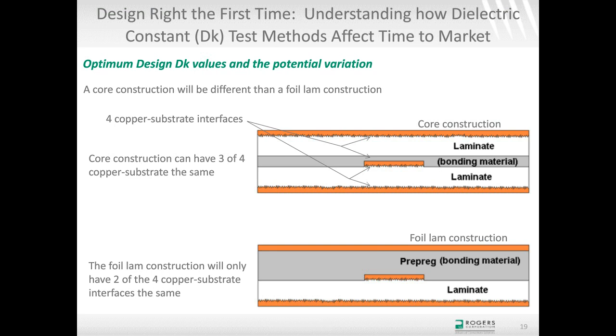In that case, we understand and we would know the copper surface roughness of three of the four copper substrate interfaces. We would not know the fourth one, which would be the smooth side of the bottom laminate. And the reason we say that is because we know what that smooth copper is. We know what that surface roughness is when it leaves our facility as a laminate. But in making a stripline circuit, they typically will alter that surface with an alternative oxide or something to enhance the bonding. And that does affect the copper surface roughness.